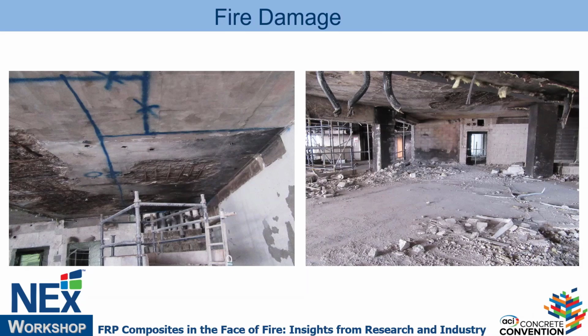Here are some of the fires that I've been exposed to. You can see the damage is really not uniform, right? Because fire is a function of the fuel. And when you have concentration of heat, in some locations you may get significant spalling, and in other areas you may see no spalling. So it varies a lot, and I think that's why concrete structures sometimes can last, because the damage is not uniform. Some areas may still be adequately anchored and can last very long. There is moment redistribution, and all different effects that give us some resistance. Plus we don't have the full live load, right? Even on regular days, we never really have full live load on a structure when we design in service.